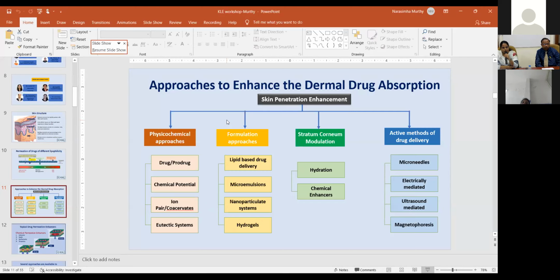polymer-based microneedle. After you make the microneedles, you can calculate based on the volume of the microneedle, the dimensions of the mold, the density of your solution, and the amount of drug that you incorporated into the solution. You would be able to calculate, theoretically, how much drug should be present in the microneedles. And then, of course, in every batch, like how you test the tablets, per se, you're making 1 lakh tablets, you would take out 20 tablets and test for the drug content. You would do the same thing with the microneedles as well. You have to scrape out the needles and look at the amount of drug present in that.